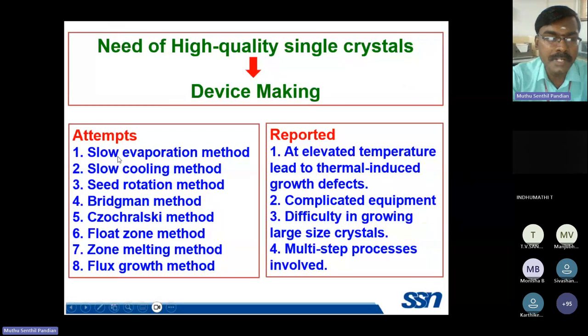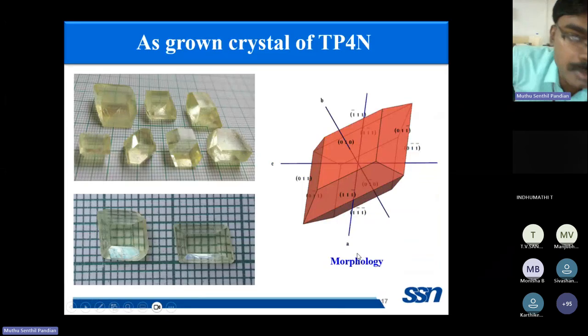wafers. Several attempts have been made to grow crystals by the slow evaporation method, slow cooling method, seed rotation, and melt growth methods like Bridgman, Czochralski, floating zone, zone melting, and flux growth method. But all the reported methods are at elevated temperature, which leads to thermally induced growth defects, very complicated equipment, and difficulty in growing large size single crystals. There are also a lot of multi-step processes involved when you grow the crystal by this melt growth technique.